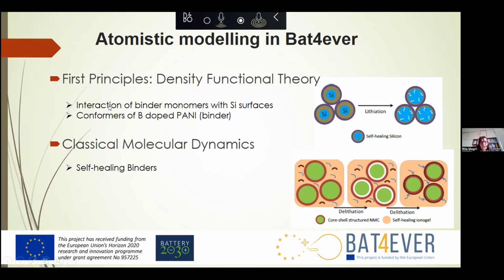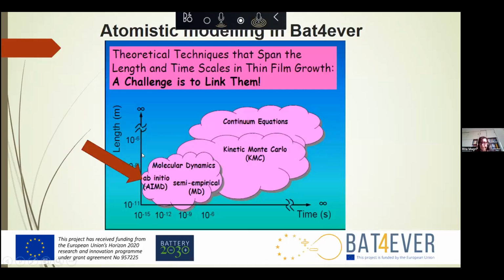We have studied the interaction of monomers of some binder proposed by our partners on silicon surfaces, and also some conformational studies of optimization of these monomers. And then we have used the monomers to simulate also some dynamics of these monomers at different temperatures and different conditions using classical molecular dynamics.